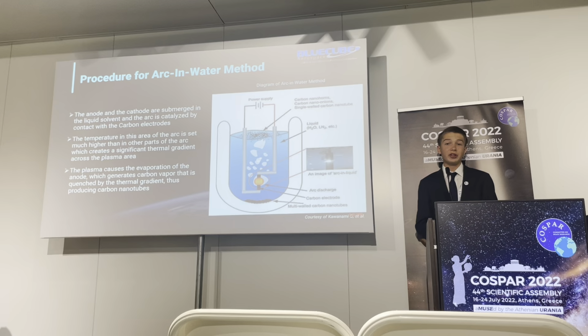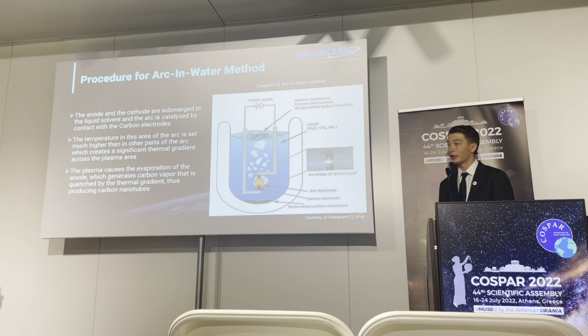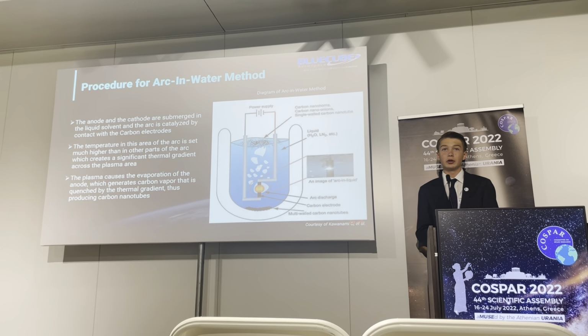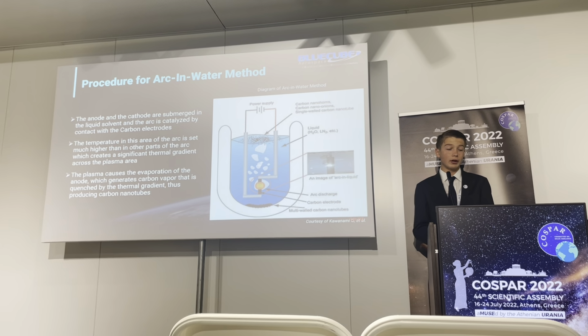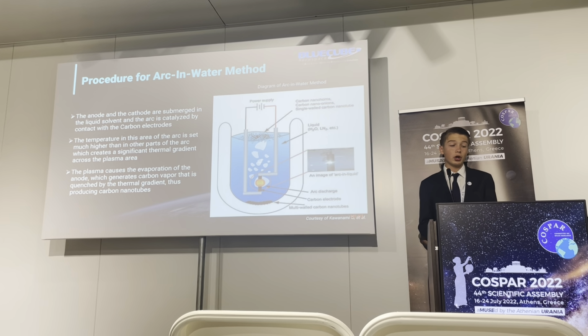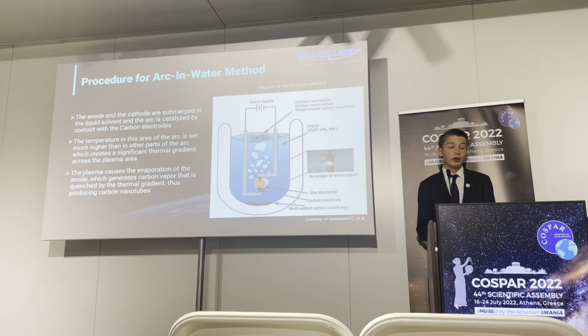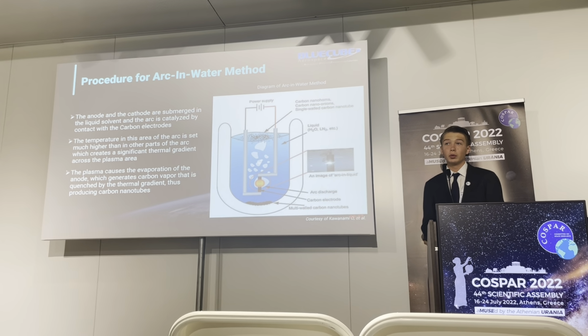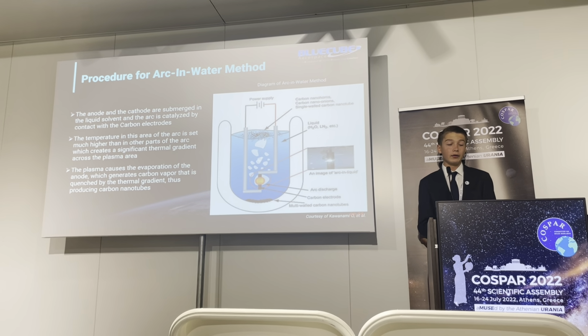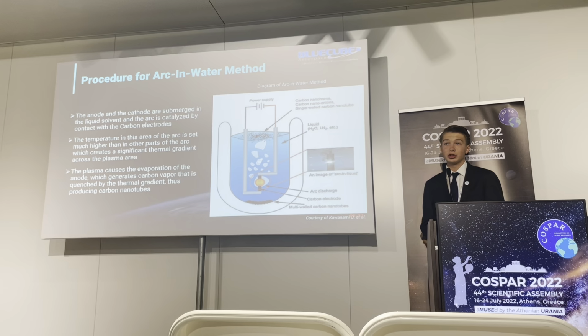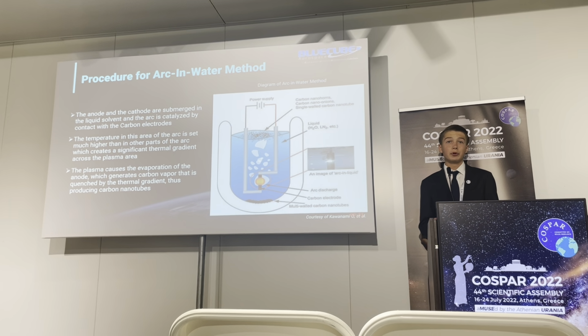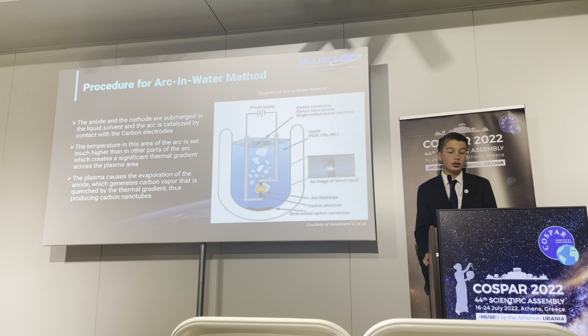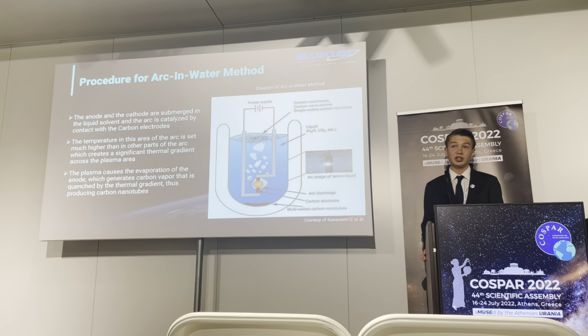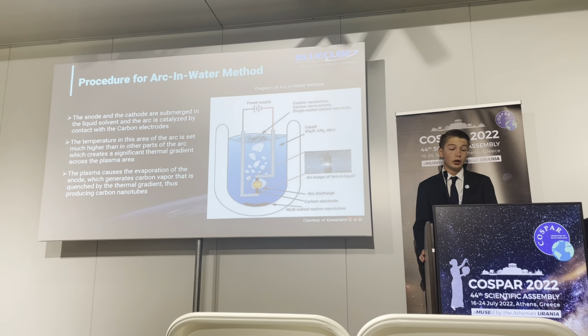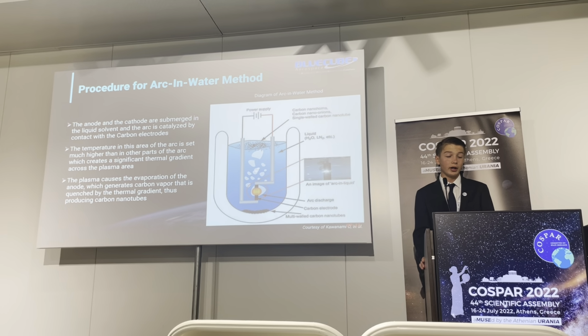This method specifically targets the production of graphene, but can also produce other related nanomaterials. So as I mentioned, this method requires minimal materials in order to produce graphene. It starts with carbon electrodes. The anode and the cathode are first submerged into a liquid solvent, and then the arc is catalyzed by contact with these carbon electrodes. The temperature in this area of the arc is then set much higher than other parts of the arc, which creates plasma and a significant thermal gradient across this area.